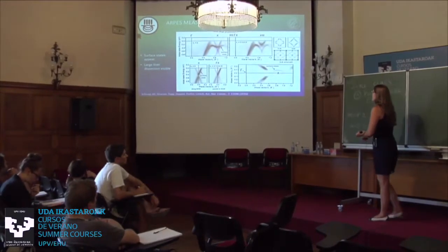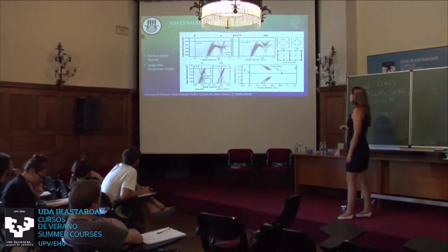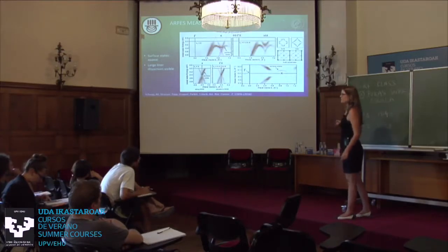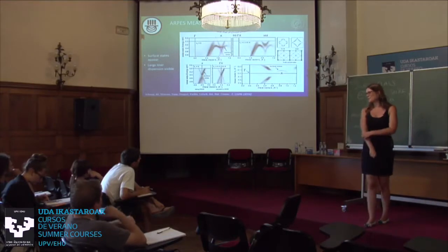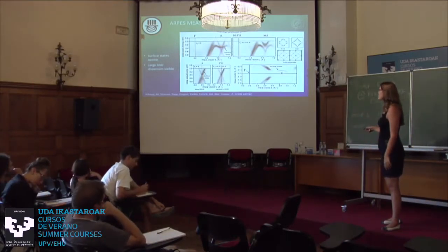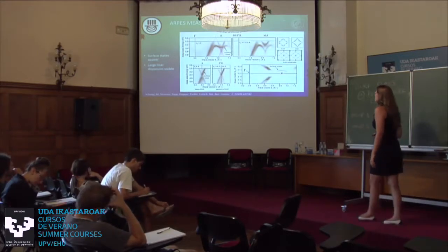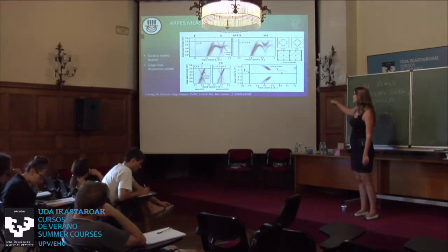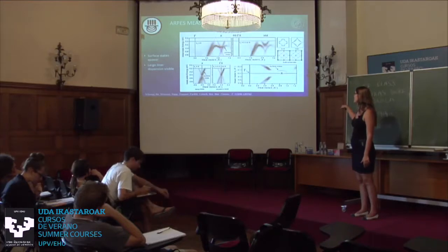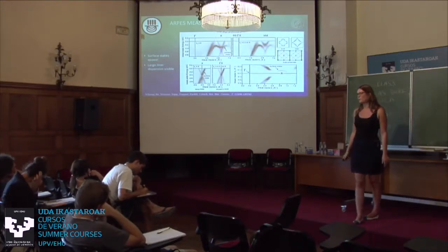So then the next step was to measure the ARPES spectra, and so you can see here the in-house data. By the way, here you see how the data looks kind of ugly and stepwise, which is because this is the cut along this angle we tilted, so it's not smooth data, so the measured direction is here where we have nicer data. Anyway, the purple lines here are the states we expected from the DFT, and then there are the additional states here and here, which we didn't expect from DFT.